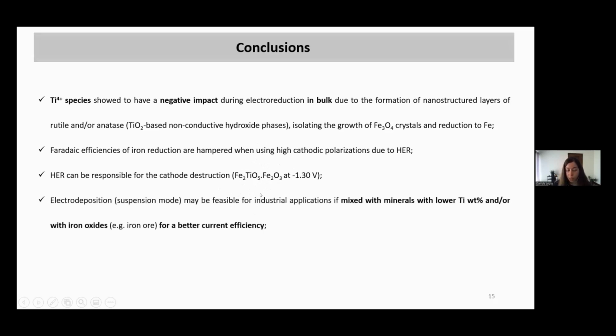So in suspension mode, we obtain metallic iron. However, pseudobrookite doesn't look feasible to be used at pilot plant scale. I also have to say that pseudobrookite has a high content of titanium oxide. So in the future, we are seeking to use materials with lower content of titanium, because probably it will not have such a strong effect. And we can mix it with iron oxides, hematite, or iron ore to improve the current efficiencies, and like this maybe it can be useful for the pilot plants.